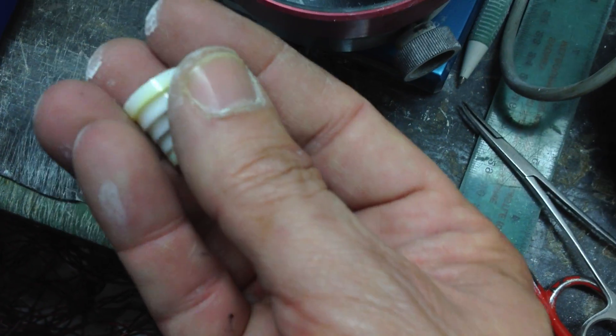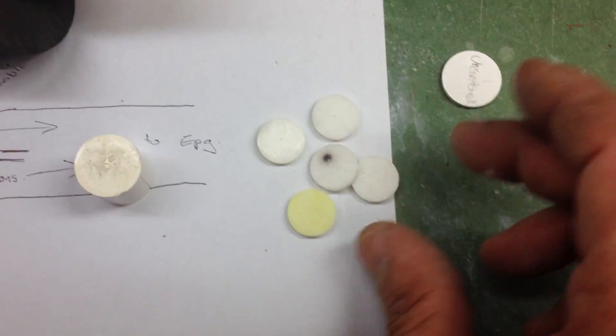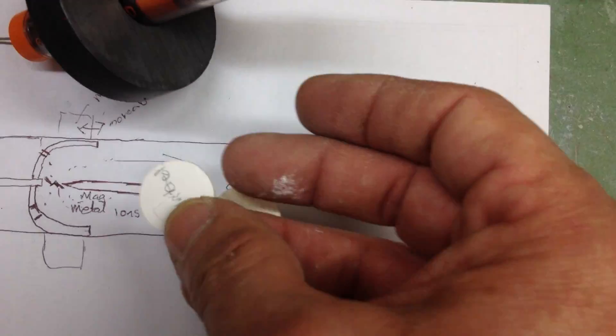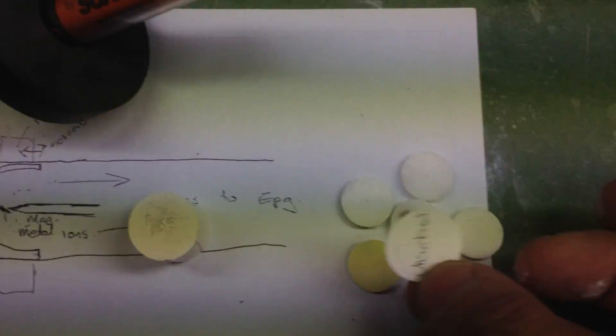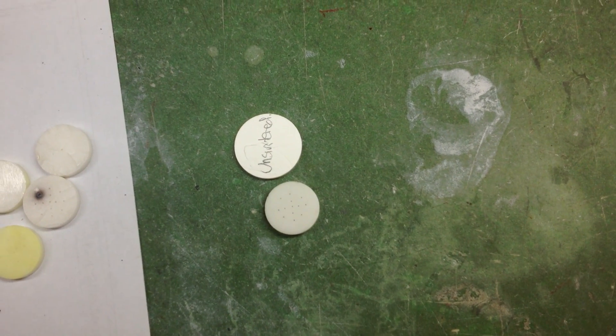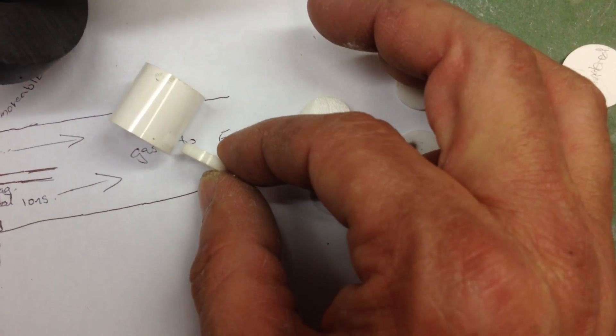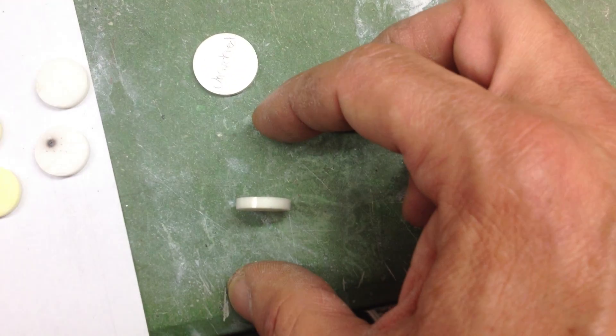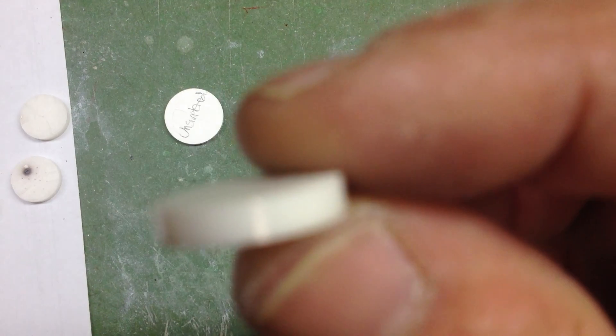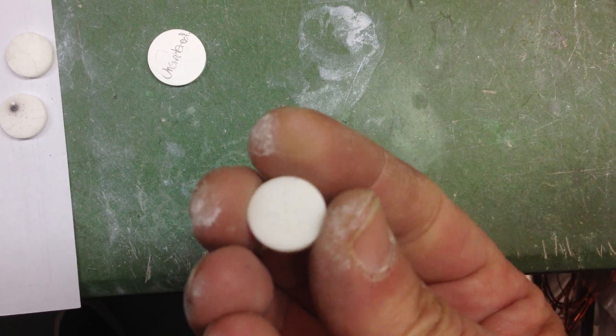There's five discs, Max. They're coming your way. I'll send you a piece of unsintered disc as well, which is a piece of that before it goes into the furnace. As you can see, the size difference is a lot. That's the same size as that. And after sintering, that's the size you get. And it also shrinks that way. Of course that's not one of those, but this was 20% bigger that way before sintering than it is now, but these ones came out quite nice, fairly sharp edged. They should be good.